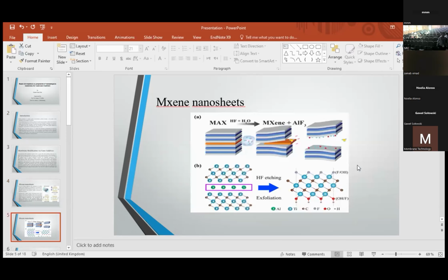As shown in this figure, MXenes are two-dimensional layered carbides or nitrides produced by carefully etching away aluminum layers from the MAX phase. As shown in the figure, the formula of MXene is Ti3C2Tx. The Tx stands for the surface modification like OH, O, and F functional group. These materials are often created by extraction of the aluminum layer from the MAX phase.